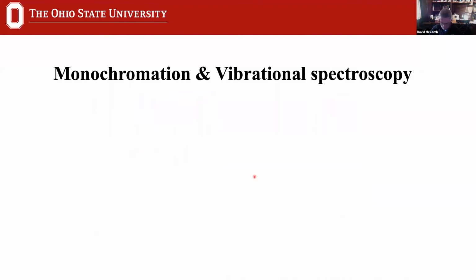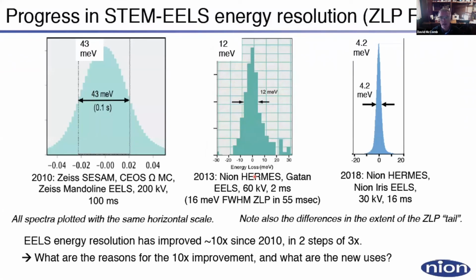So in the last 5 or 10 minutes, I want to touch a little on some of the new capabilities that are coming into EELS, and we're now seeing the potential of them. Let's go back to monochromation again, with a slide that I borrowed from Ondrej Krivanek at NION, showing the evolution in, for example, the NION systems of where we've got to in terms of energy resolution. Again, we're looking at our zero loss peak, and we can see that most recently we're down to, as I mentioned at the beginning, sub 5 millielectron volts in terms of full width at half maximum. So we've seen big improvements in this over the last couple of years, and we continue to see improvements as these instruments just get better and better.